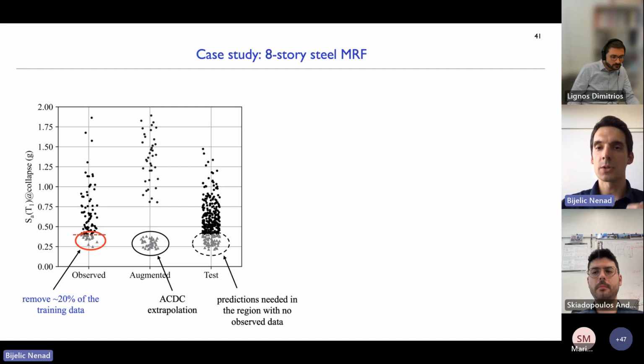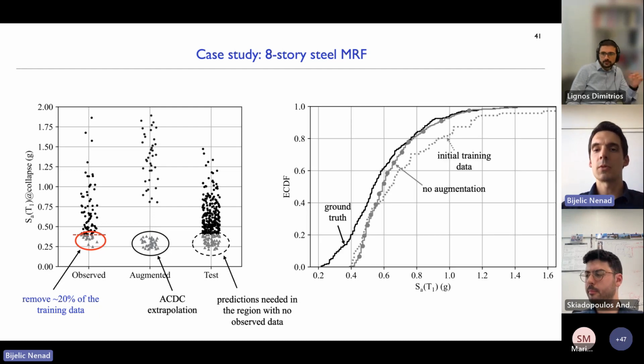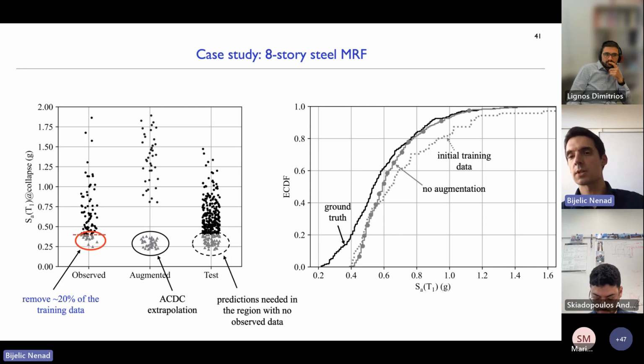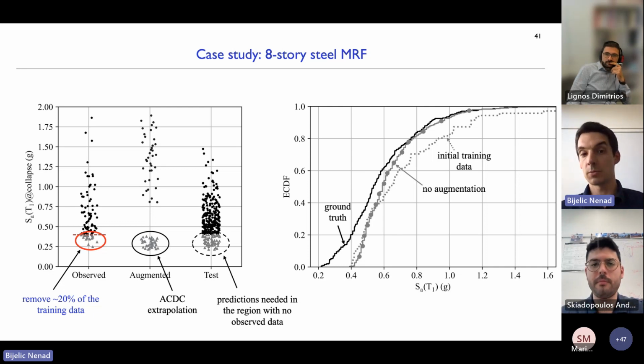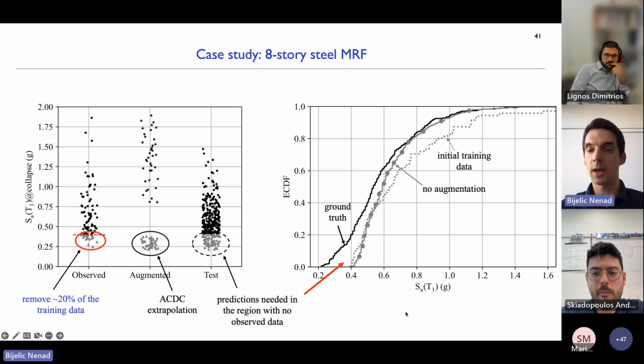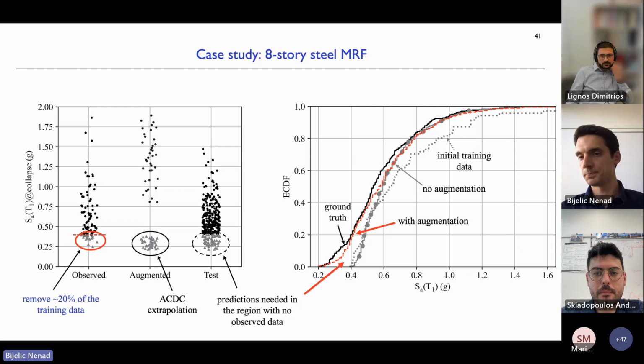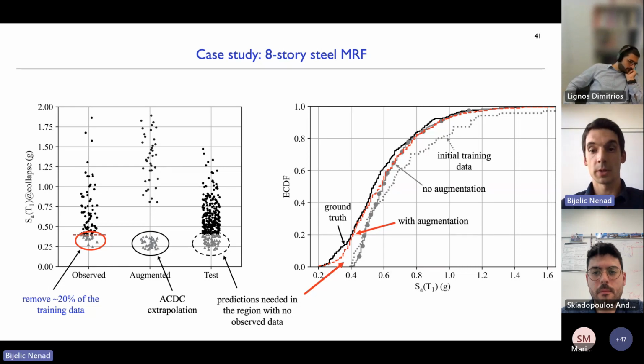Okay, so here's the result. You've seen this figure before. We see the ground truth, the initial training data in a dotted line, and then the prediction of an XGBoost classifier with no augmentation. We see that the problem is in the region where we don't have any data, because the predictor can't predict anything where it hasn't seen data. That's what's tripping it up. But if we add the AC/DC augmentation, then we get a much better predictor in this region. So that's pretty cool.